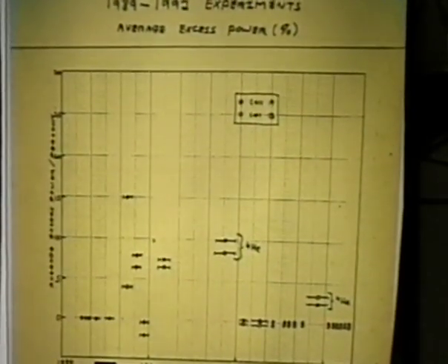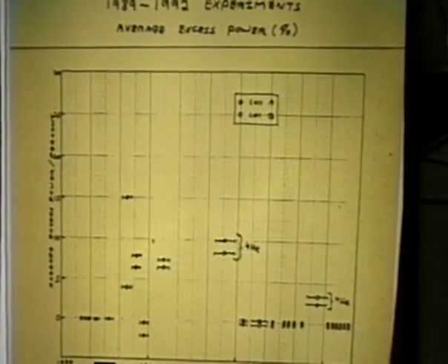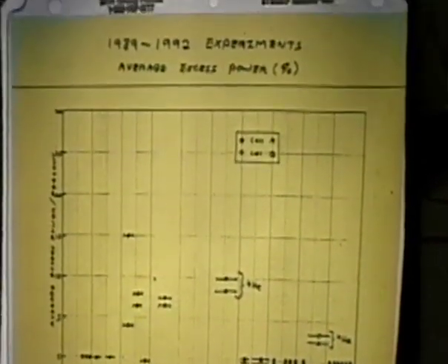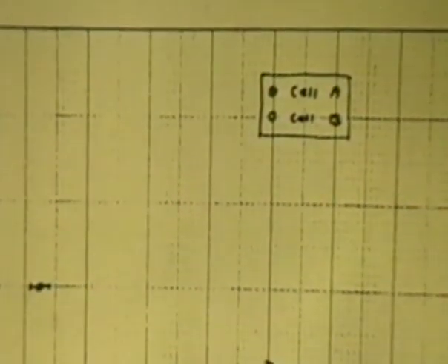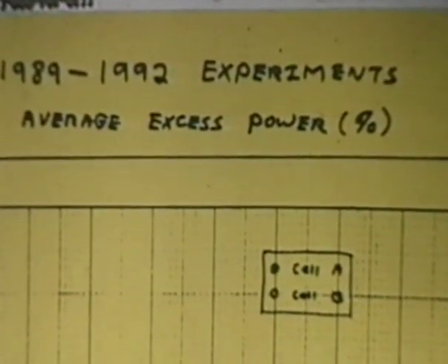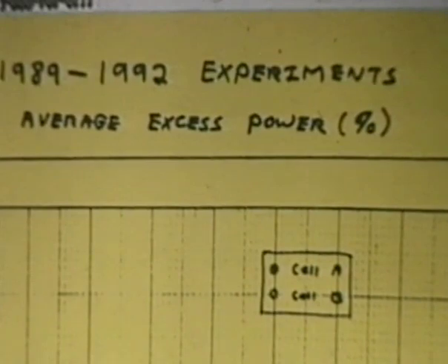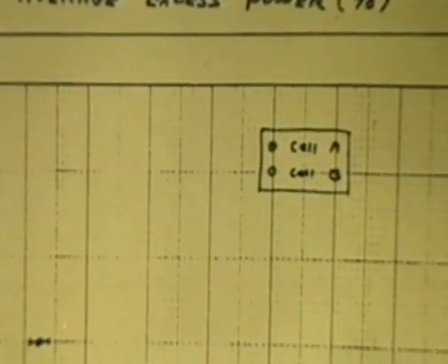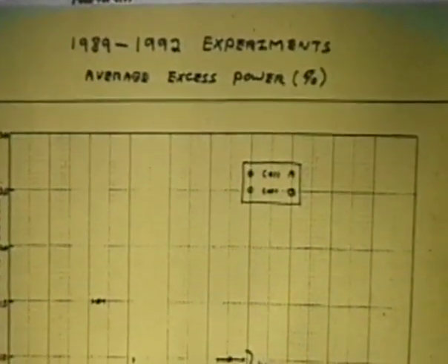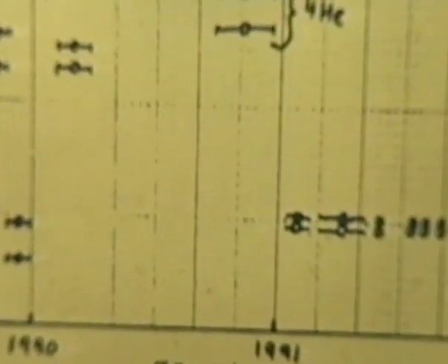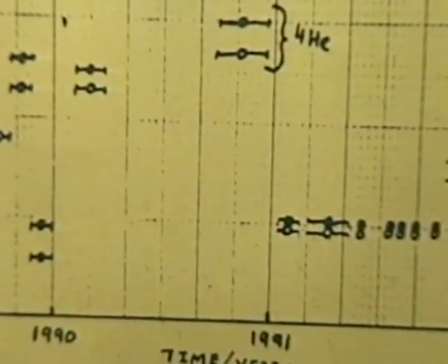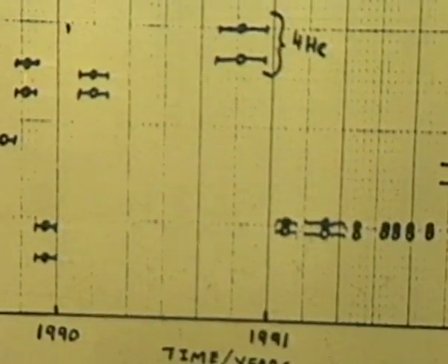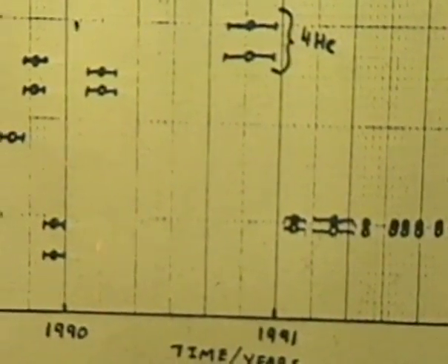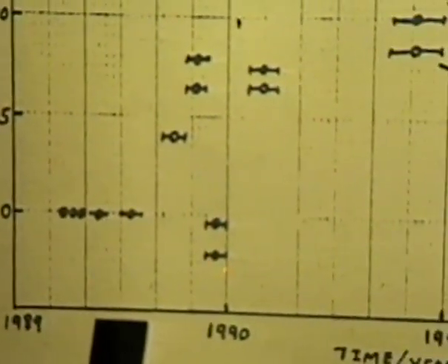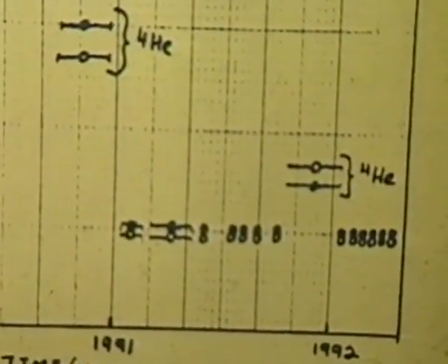This summarizes some of our early experiments. Starting off in 1989, using the old palladium we had on hand, we never got excess heat. When we got the new palladium, these are averages right here. The one experiment averaged 15% throughout the experiment. That was cell A. The other cell averaged lower. But we did get up to 30% for certain periods in that experiment. Then later we repeated this, got excess heat again, not as much. We ran H2O as a control, and that averaged out to break even. Then we ran a third experiment and got excess heat again.